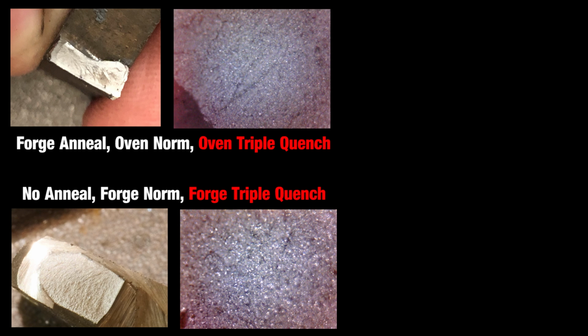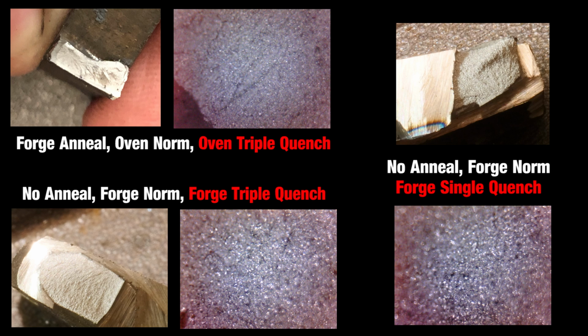No anneal, forge norm, triple quench from the forge. Pretty good results, but compared to the oven triple quench, here's a no anneal, forge normalization, single quench. So I think you can see the sequence there of awesome to not quite as awesome.